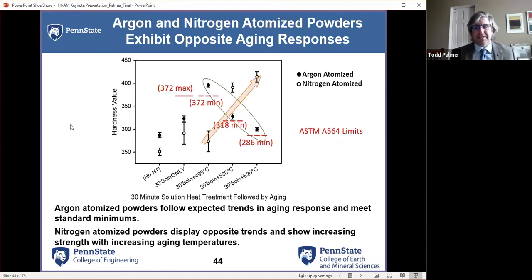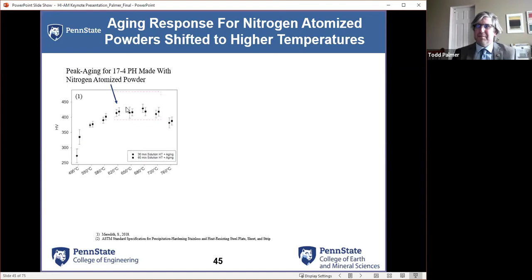Now, what really flummoxed us a little bit was the appearance of all this retained austenite when we tried to run these through traditional post-process heat aging treatment. So you have to solutionize and age the materials after they're done in order to obtain the properties you want. What we found was that the argon atomized behaved as expected. That's right on: you should get a peak aging at about 495, and it should decrease as you move your way down. Nitrogen acted in the opposite way, which really got us thinking, okay, why is that? So it's telling us that we actually underaged when we thought we were peak aging in the nitrogen atomized. So we had to keep going up in temperature, and we found that we end up with a peak aging condition, and the hardness matches that peak aging condition somewhere around 620 to 650 degrees C. The literature was telling everybody that you couldn't age nitrogen atomized materials. We really came to say you need to age them properly is a better way to do that.